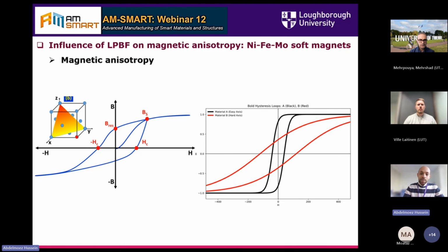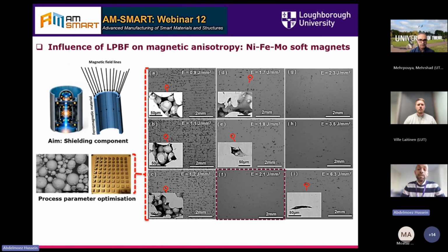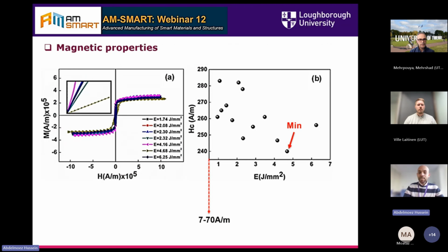So how can laser powder bed fusion affect the magnetic anisotropy? One of the examples that we faced was for magnetic shielding, using permalloy, nickel iron molybdenum, to make a component for magnetic shielding. So we start normally from powder, pass through a design of experiment, and optimize the laser parameters, and we find a good condition, which is letter F. Now we achieve a minimum porosity. So let's discover the magnetic properties, which is the logical step.